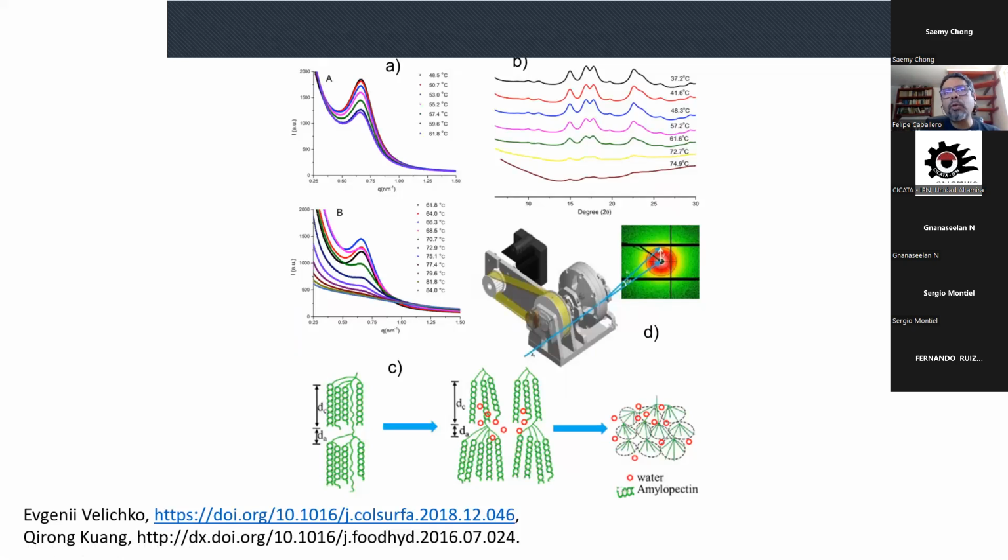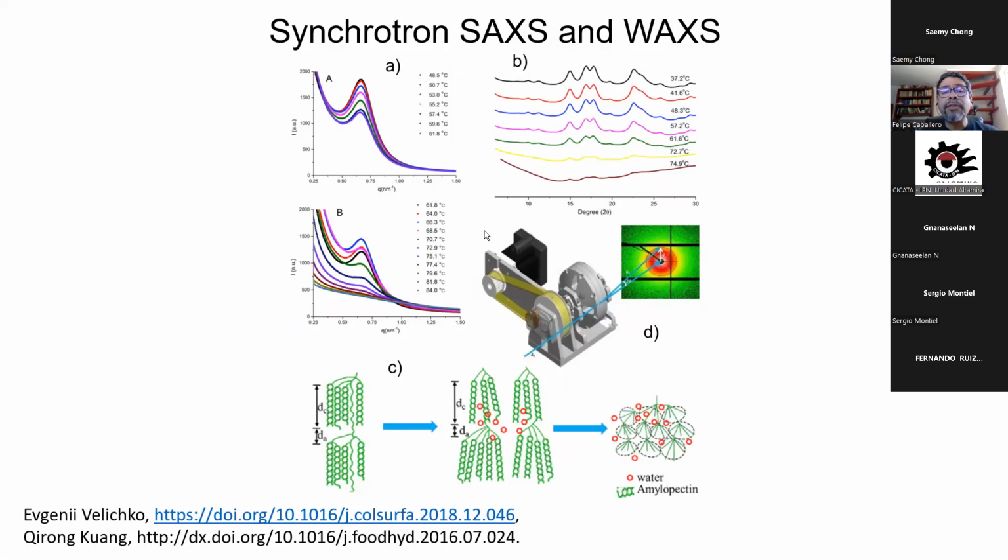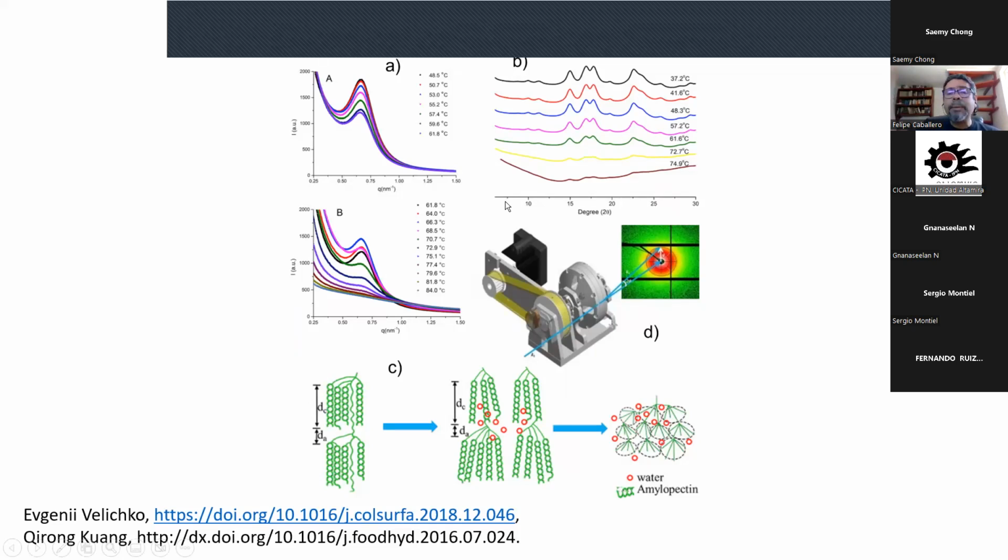So we are used to working in our laboratories with wide angle X-ray scattering, or X-ray diffraction, from 5 degrees up to 30, 40, 70 degrees, that is useful to observe inorganic structures. Because as you remember, the plane distance is inverse to the diffraction angle. So smaller lattice constants are observed at bigger diffraction angles, for example, in inorganic crystals.